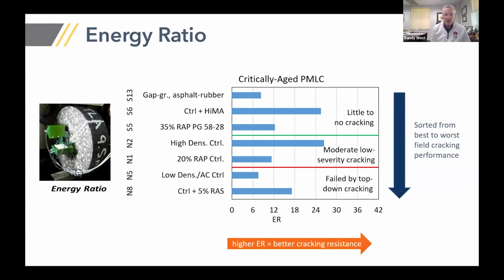It's an indirect tensile type test, but with strain gauge extensometers that are glued to the specimen face. What I'm showing on the right is this chart that Nathan illustrated a little while ago as well. The 7 mixes are ranked here from top to bottom by best performance at the top, worst performance at the bottom. And the top 3 mixes in this had little to no cracking. The 2 in the middle had moderate, low severity cracking, and the bottom 2 mixes in these charts failed by top-down cracking, and those were all verified by cores.